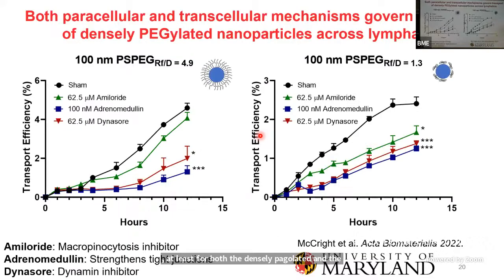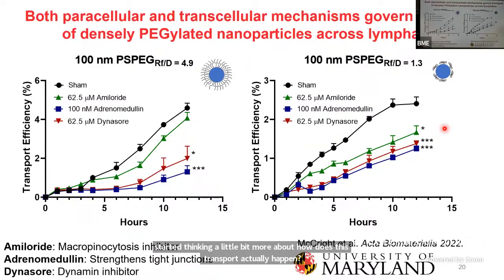Now, when we looked at this with our lower PEG density particles, we actually saw some interesting differences. So we found that here, similar to the densely pegylated particles, you have paracellular transport and micropinocytosis that's reduced when you add the transport inhibitors. But here for the less densely pegylated particles, you also can see that there's a reduction in macropinocytosis. So if you inhibit macropinocytosis, you get fewer nanoparticles transported across the lymphatic endothelial cells. So this indicates that there's definitely a surface chemistry dependent mechanism that's happening here.